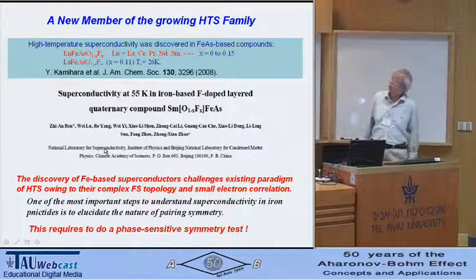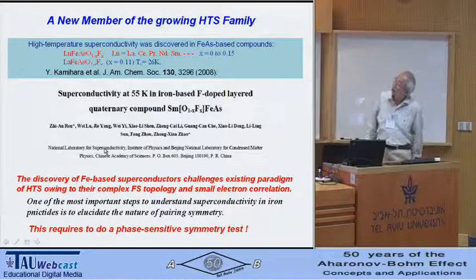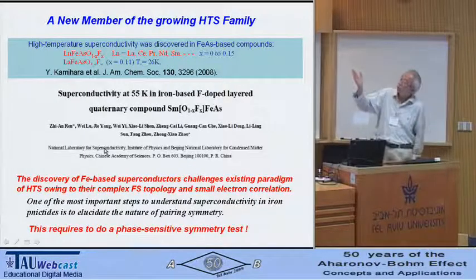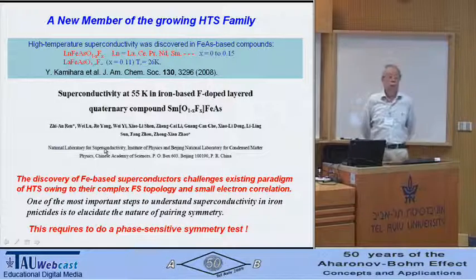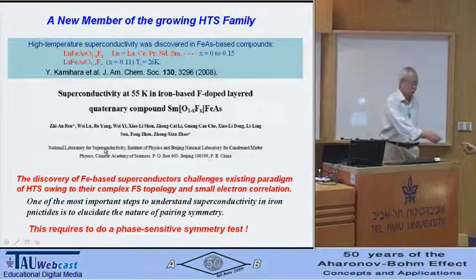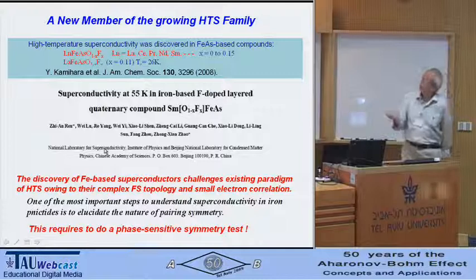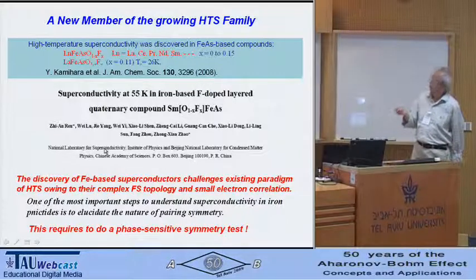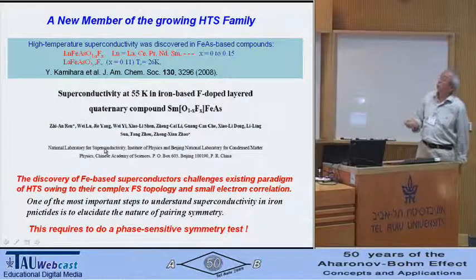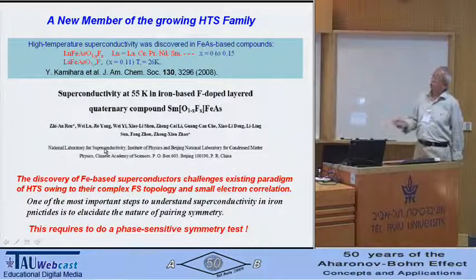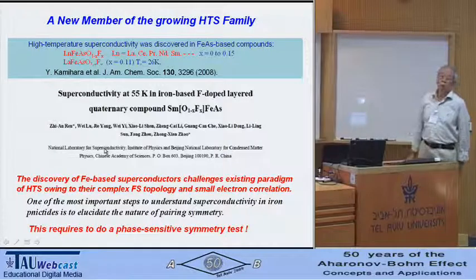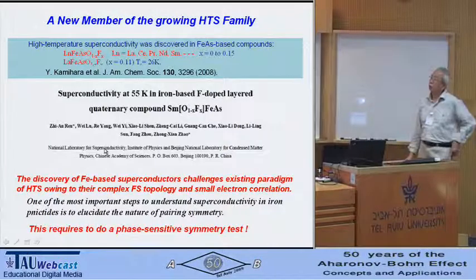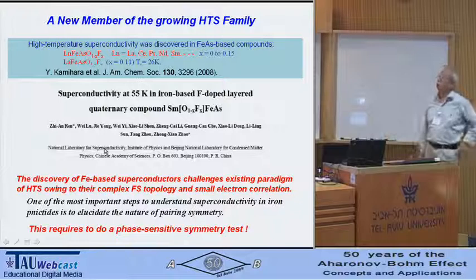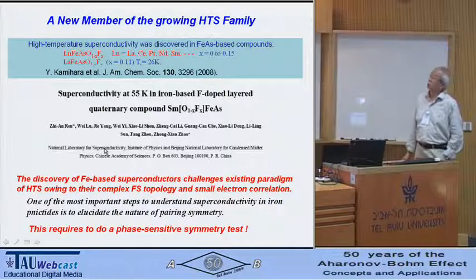Here's the formula. As an example, lanthanum, iron, arsenic, oxygen, fluorine. It's doped with fluorine, with a TC of 26 degrees K. That was discovered a little bit over a year ago, and that caused a lot of interest.